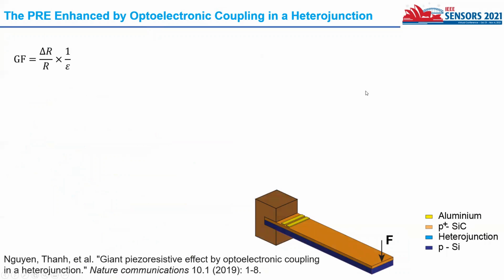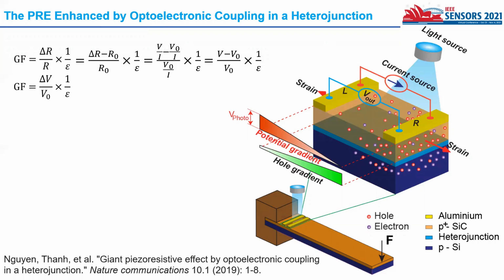Recently, our group used optoelectronic coupling in a heterojunction to enhance the performance of the piezoresistive effect, which has been published in Nature Communications. To enhance the piezoresistive effect, we combine light illumination, which is applied non-uniformly to the sensing element, and we also couple it with a tuning current to enhance the performance of the piezoresistive effect.